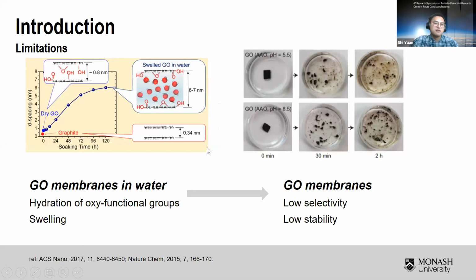However, when we use GO membranes in water, the hydration of oxygen functional groups will lead to significant swelling of GO. The interlayer space, which is the size of the 2D nanochannel, will increase from sub-nanometer to several nanometers, which will lead to a decrease in selectivity and stability. And if we apply a GO membrane in water for a long time, it will even redisperse into the water.